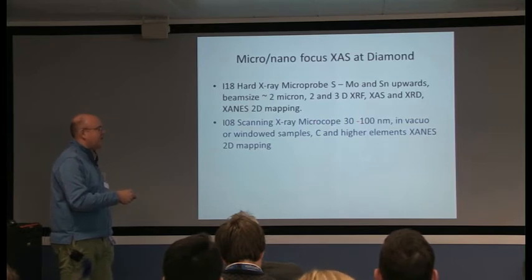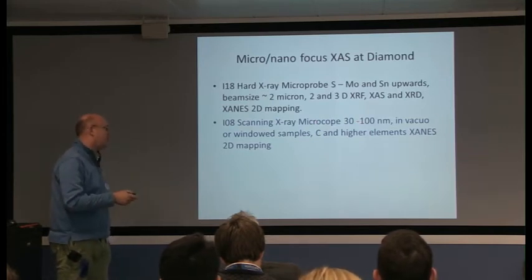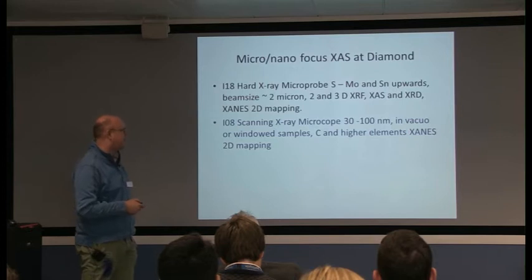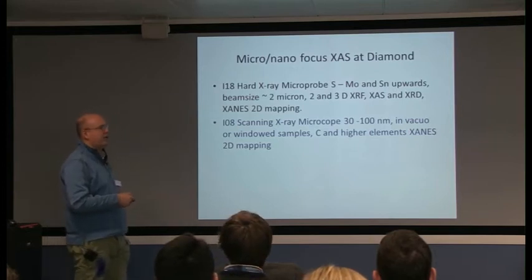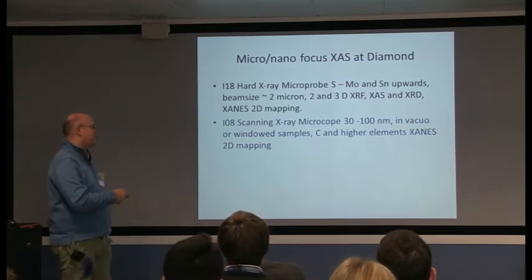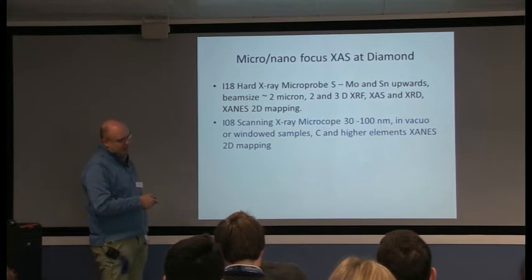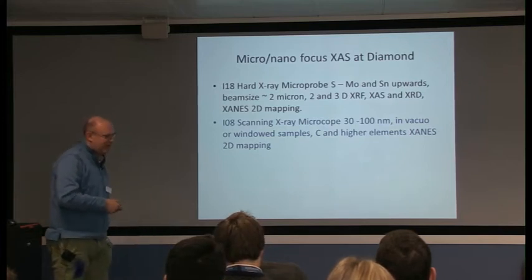30 to 100 nanometers. It's normally run with the samples in vacuum, though you can make a sandwich parcel, as I'll show a bit later. It can scan carbon and higher elements, so it's looking at softer edges. It goes up to 4K, so it can just do the calcium K edge.